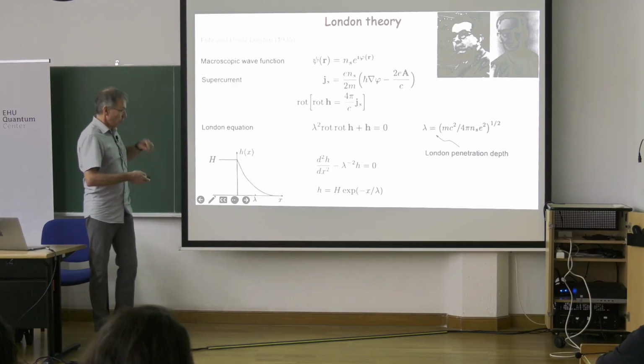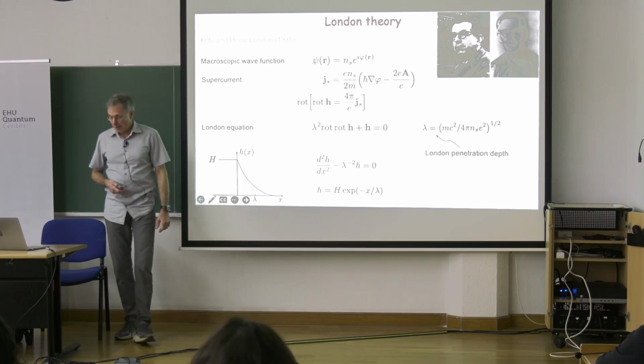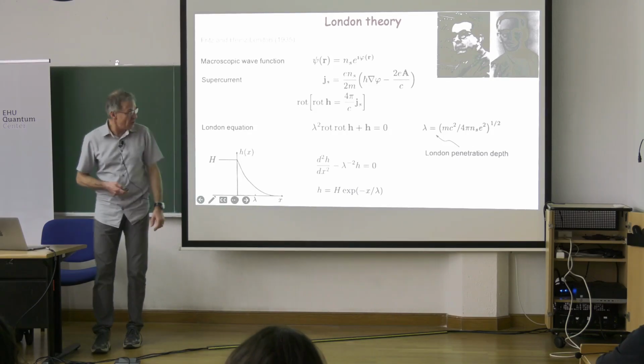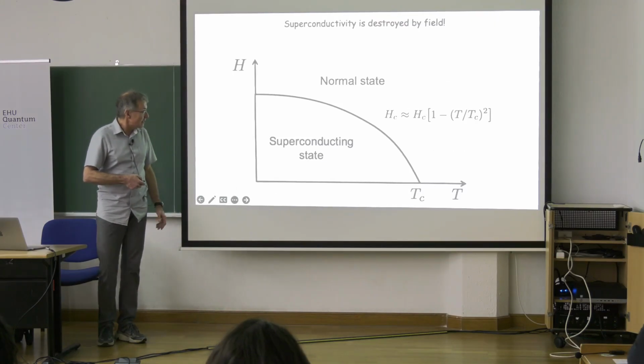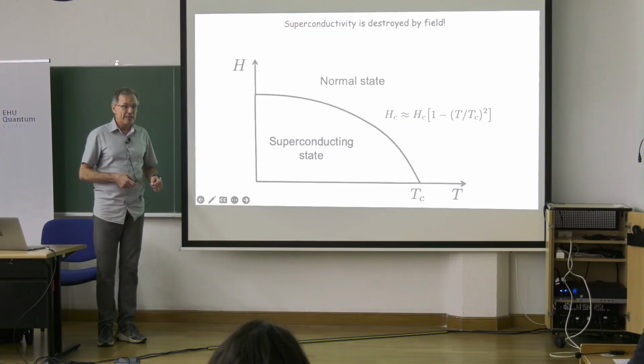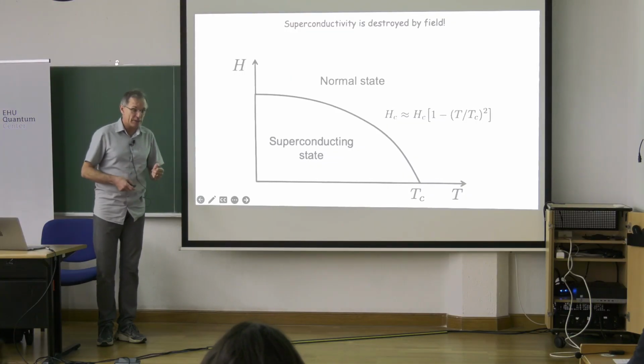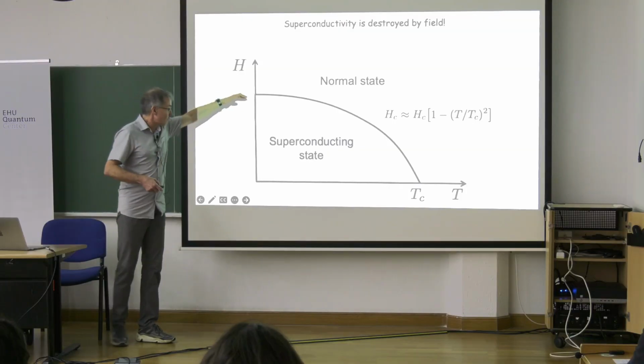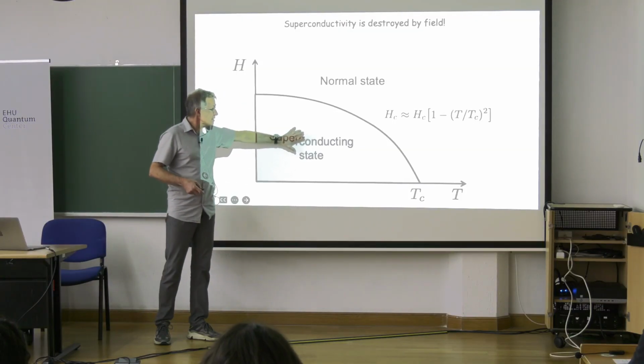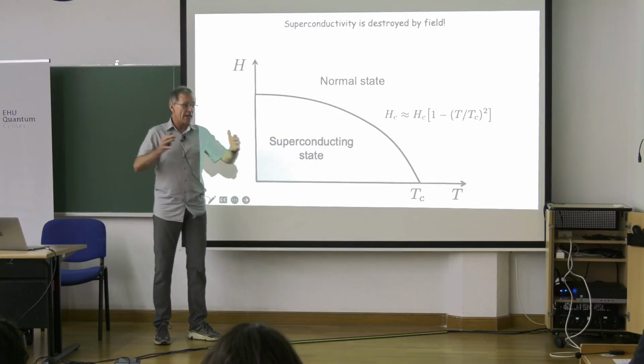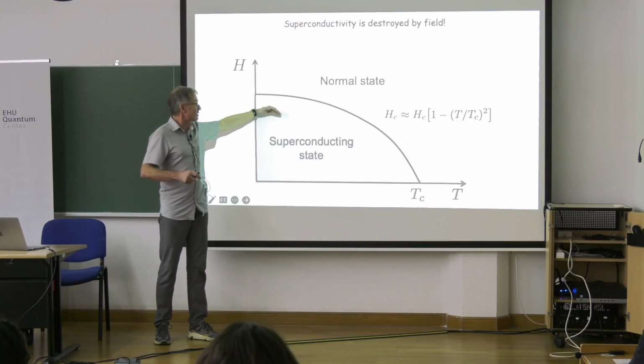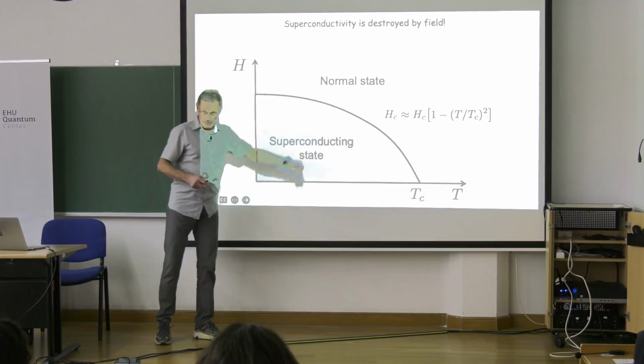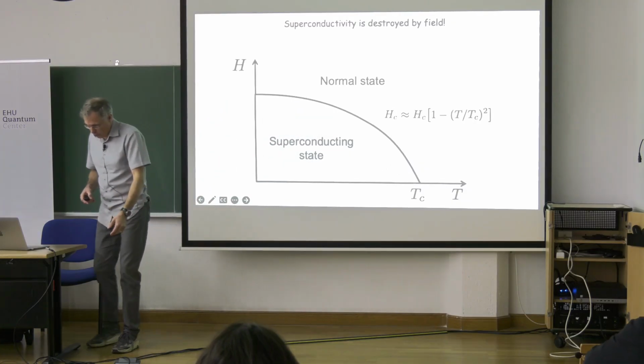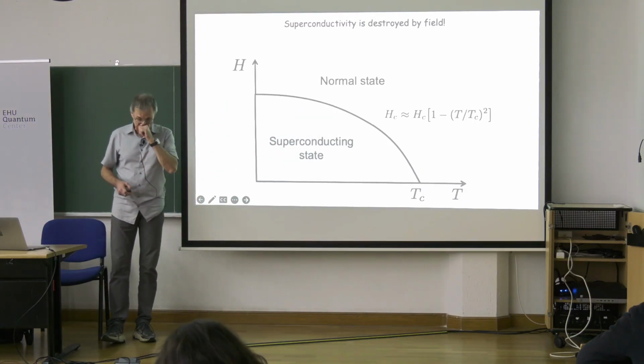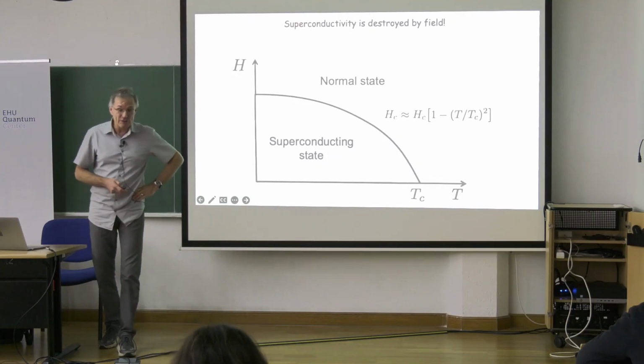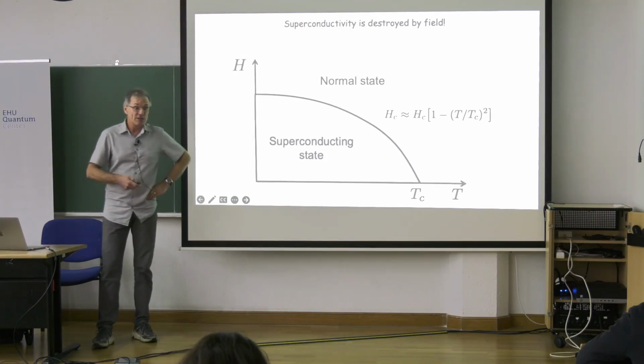So that's what happens if we apply rather weak magnetic field. Now, if we apply high magnetic field, then actually this magnetic field can kill superconductivity. Here we have superconducting state for low field, which expels the field. But if the field is higher than some value, then our metal goes back to a normal metal state. It's quite interesting how this critical field was actually discovered.